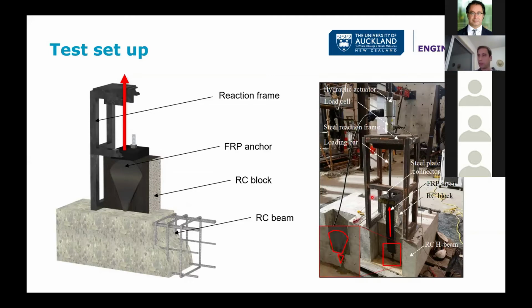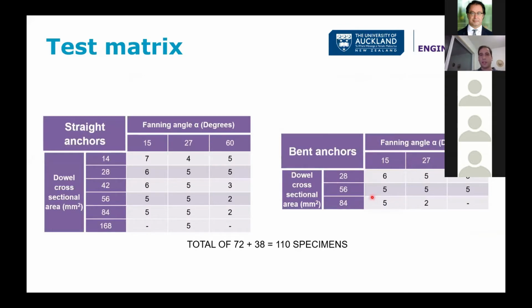So I spent a whole lot of time in the lab, getting my hands dirty, installing FRP, breaking FRP, and I ended up with 110 specimens, 72 for straight anchors and 38 for bent anchors. Now, in terms of fan angle alpha, I looked at 3 different angles, 15, 27, and 60. 27 because it's as wide as long. And then for straight anchors, I looked at different sizes from 14, this is dowel cross-sectional area, by the way, from 14 square millimeters all the way to 168 square millimeters. However, for bent anchors, when I started to get to 84 square millimeters, the efficiency was very low, something like 40% or 45%.